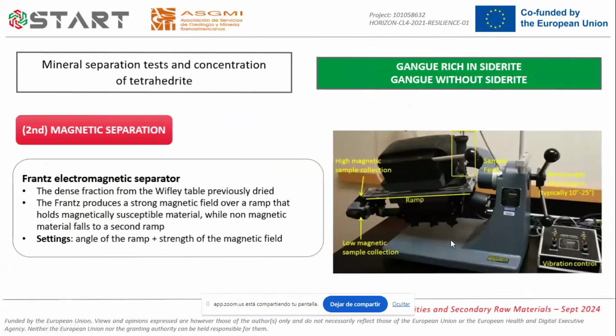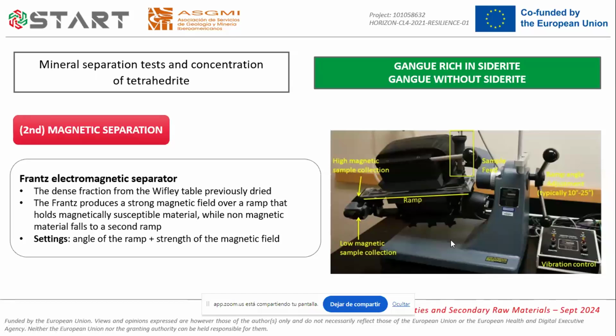The next step is the magnetic separation, and it has to be followed in both cases or in both types of sites. To carry out this separation, we use the Frantz electromagnetic separator. The dense fraction from the Wilfley table has to be previously dried, of course. The Frantz produces a strong magnetic field over a ramp that holds magnetically susceptible material, while non-magnetic material falls to a second ramp. Here we have a diagram of the different parts of the equipment. We can control the angle of the ramp and the strength of the magnetic field.